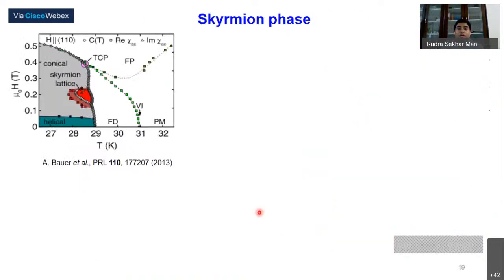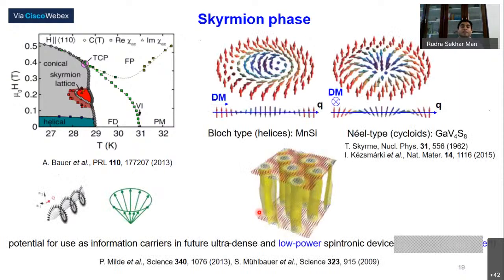And I will show a couple of other phases where the spins can orient in a very fascinating, very exotic fashion. You can see this particular phase in the phase diagram. This is a material called MnSi, manganese silicide, where you have magnetic field and temperature. Here, in this red zone, there are other phases where the spins can have conical or helical structures. Here is the helical phase, and here you have a conical phase. But in this particular block marked in red, the spins show a very unusual phenomenon or structure, which you can see.